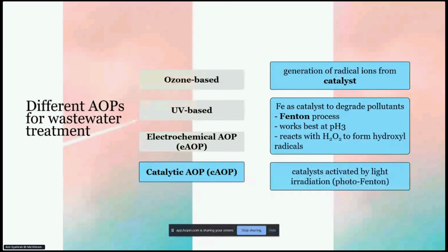And lastly is the catalytic AOP. In a catalytic oxidation process, a potential catalyst is used to generate radical ions. For example, iron can be used as a catalyst to degrade pollutants. This process is called a Fenton process. A study carried out in 2014 recorded that the catalytic activity of the iron was at maximum at pH 3, when the ferric oxyhydroxide precipitates. During the Fenton process, the ferrous ions will react with hydrogen peroxide to generate hydroxyl radicals. However, excessive hydrogen peroxide can lead to reduction of iron 3 to iron 2, which will affect the generation of radical ions.